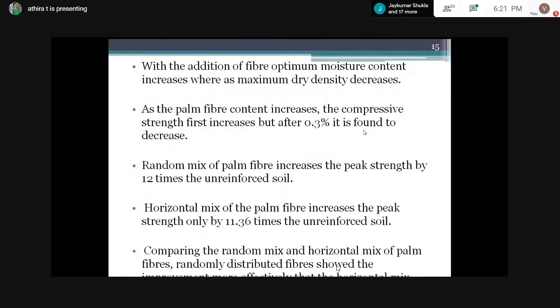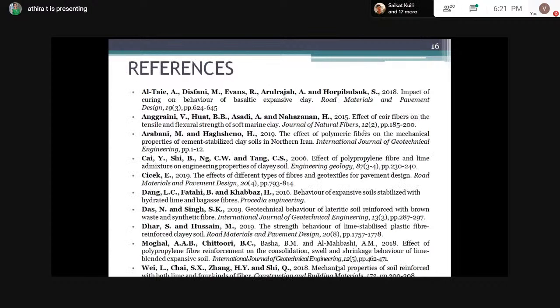The random mix of palm fiber increases the peak strength by 12 times the unreinforced soil. Whereas in the case of horizontal mix, the palm fiber increases the peak strength only by 11.36 times the unreinforced soil. By comparing the random mix and horizontal mix of palm fiber, randomly distributed fibers showed the improvement more effectively than the horizontal mix. These are the references.